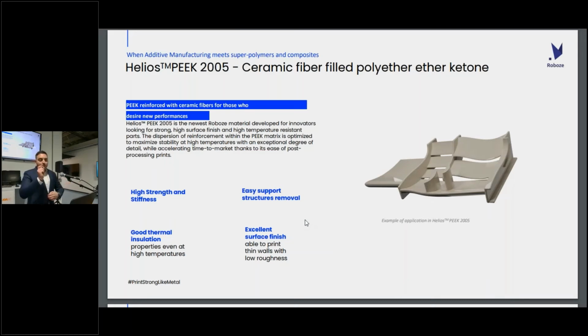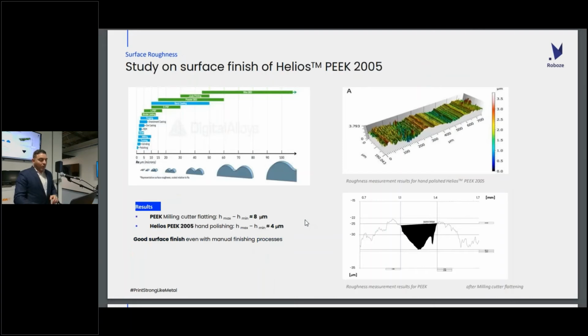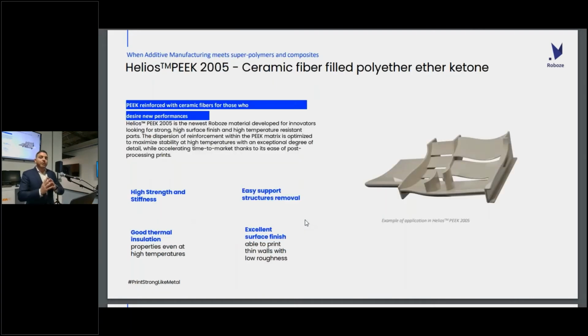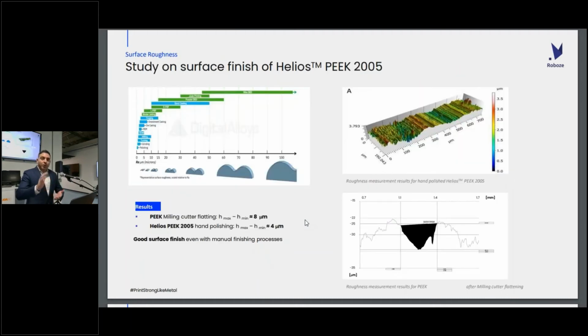So we build that specific ceramic content, that ceramic shape, to make sure that the adhesion with the polymer matrix is as high as possible, reducing part porosity and therefore increasing the strength of the material. One of the beauties of this material is that the support comes off. So it's extremely easy to post-process, and it comes with a beautiful shine. It almost looks like a lot of parts are all out of the build with just a light sanding.